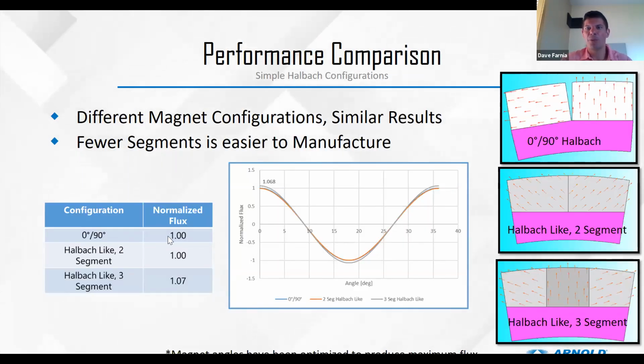If we compare that performance, let's say we have our starting point of that 0-90 degree Halbach, our 4-segment Halbach, maybe a Halbach-like, using those 45-degree angles, versus, in this case, what we call a 3-segment Halbach, performance is very similar. So we can get very similar results by using something that is a pre-bonded magnet pole compared to our original Halbach. And in the case of the 3-segment Halbach, we can actually exceed that performance.